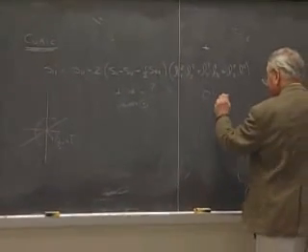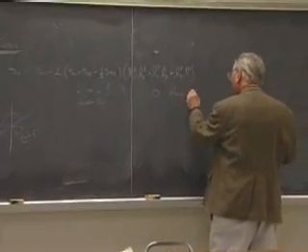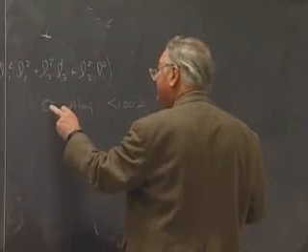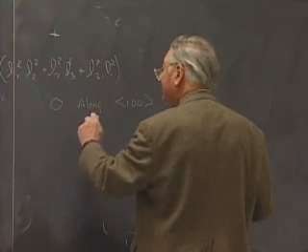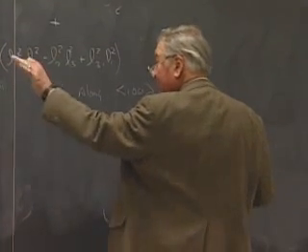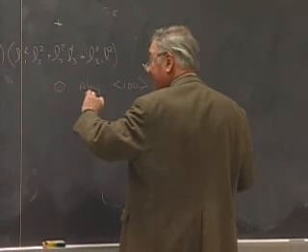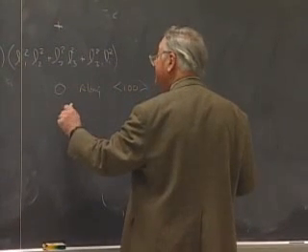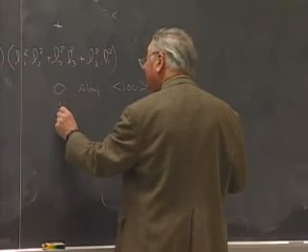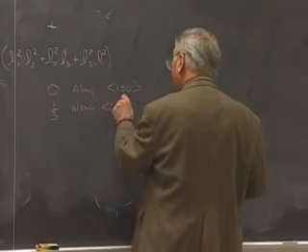And this is something that's going to be 0 along the direction 1, 0, 0 rather. So along the reference axes x1, x2, x3, which, if we remember where this form of the matrix came from, was taking the axes along the edges of the cubic crystal. It turns out that this is going to be equal to 1/3 along the direction 1, 1, 1.